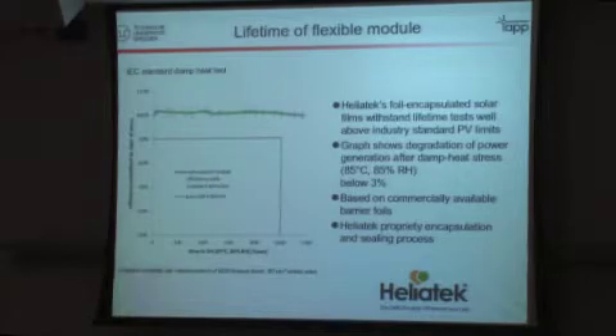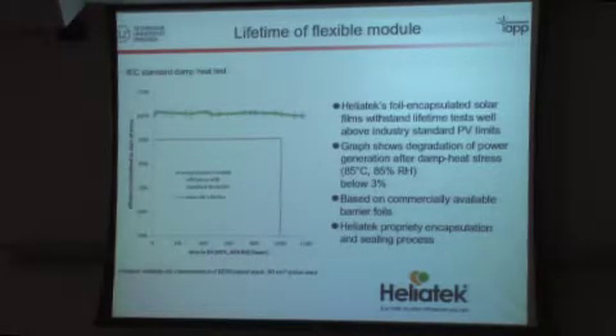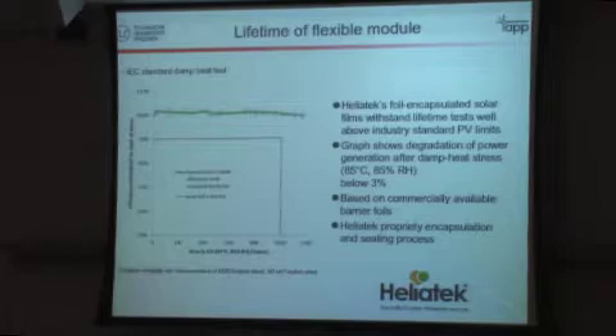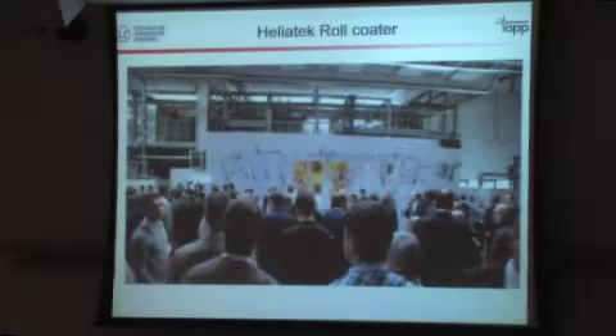There's a so-called standard damp heat test in PV, and that means that your modules must survive an 85 humidity test. For 1,000 hours, you should have at most 10% decay, and as you can see, the Heliatek modules had about 3% efficiency drops. So the Heliatek modules now pass this standard test which every PV module must pass. And the real outdoor device lifetimes are now above 10 years on foil. So I'm very optimistic that this 20 years lifetime I've named will be met.